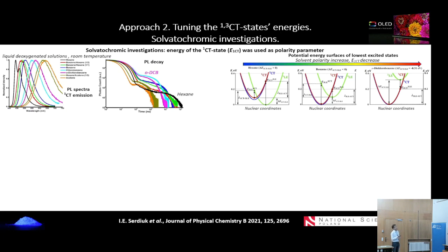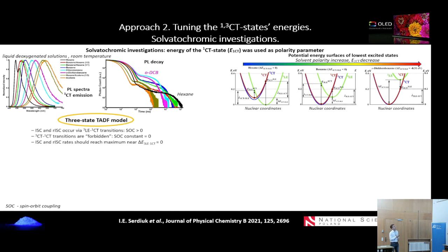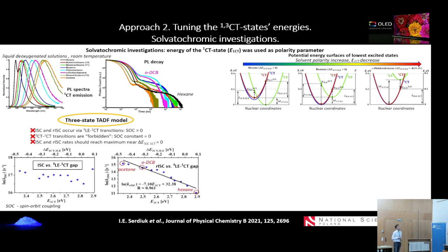And the most impressive was the result in the most polar solvents: the higher the polarity, we saw the better TADF performance. And I just want to remind you that it could not be explained by the three-state TADF model. So the LE state should be close to the CT. So we need to see the maximum somewhere here.